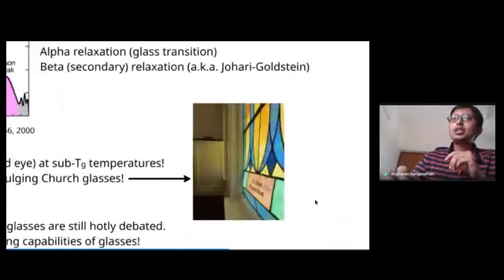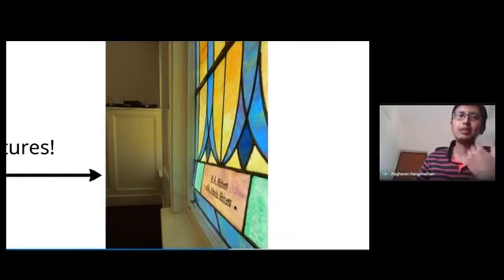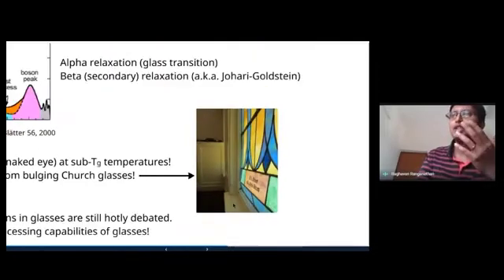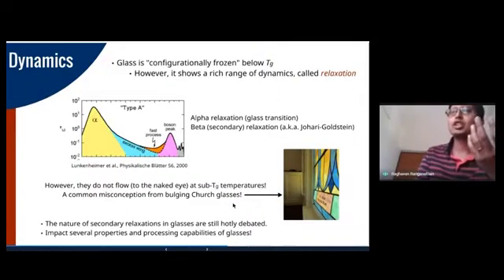And people long thought that glasses will actually flow with time. They are essentially like liquids, and given enough time, they should flow and demonstrate a more liquid-like behavior. In fact, for a very long time, people thought that the stained glasses that were used in construction, in churches and so on, had this very unique bulge towards the bottom of the panel. And people thought that was because of glass flowing with time. So these church glass walls might be a few hundred years old, and people thought that was enough for glass to flow and show a very liquid-like behavior. But it turns out that that's not really true.